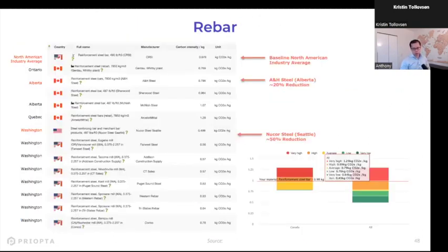I'll touch on rebar in particular, because this is a fairly big impact category, especially for concrete buildings. So if you look at the North American industry average rebar, it's about 0.979 kilograms of CO2 per kilogram. So about roughly 1 kilogram of CO2 per 1 kilogram of rebar. In Alberta, there's a manufacturer, A&H Steel, that is delivering about a 20% reduction, at least based on their EPD. If you look at Nucor Steel Seattle, in Washington, that's about the lowest carbon steel that I've seen so far, and that's about a 50% reduction. All this is to show you that there can be big variations between different manufacturers.